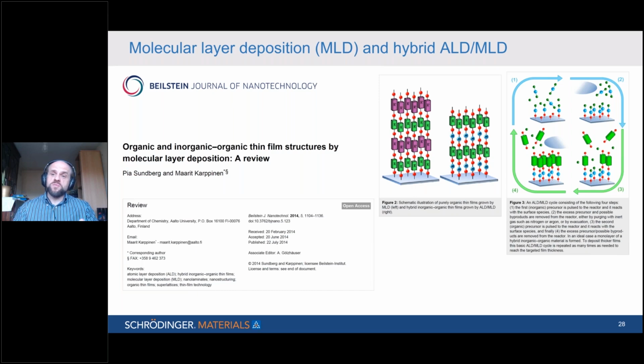So the precursors should be organic molecules, but with reactive moieties that can be used to both bind to the previous reactive surface and generate a new reactive surface for the next pulse. And a very frequently used molecule is hydroquinone, or benzene 1,4-diol. You can see it's bifunctional. It has two OH groups, so one can react with the existing surface, and the other OH group is still available for reacting with the next layer when you let in the next precursor molecule. So it's a rigid molecule that behaves like that.